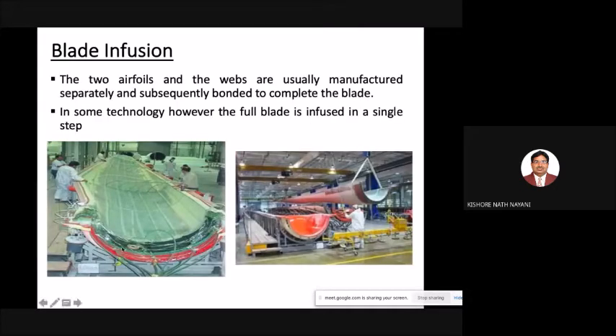So this is another important technique called blade infusion technique, which most of the industries are using. Here you can see very huge tooling for the realization of the windmill blades. The two aerofoils and the webs are usually manufactured separately and subsequently bonded to complete the blade. In some technologies, however, the full blade is infused as a single step also. Now, in order to meet the industry demand, we have to manufacture maybe 2 blades, 3 blades per day. So once you design the tool accordingly, even spars and top skin, bottom skin can be infused in a single stage also, but the tooling will be very complicated, and we have to take a lot of care so that resin flows throughout the blade and there is no defect during the realization.